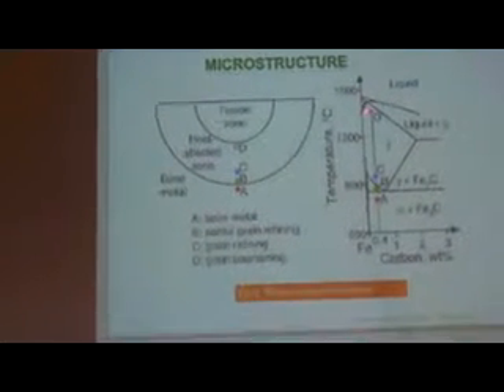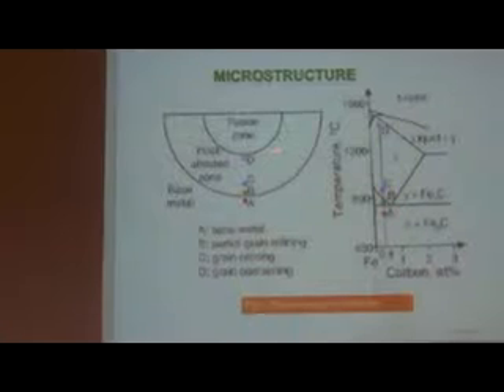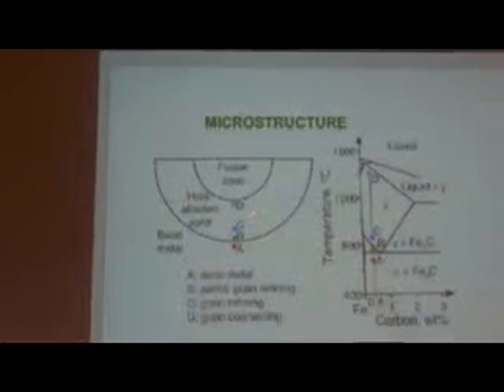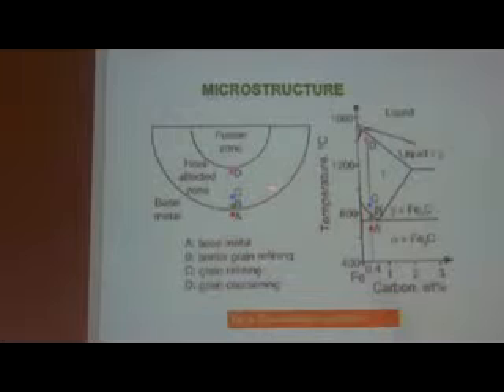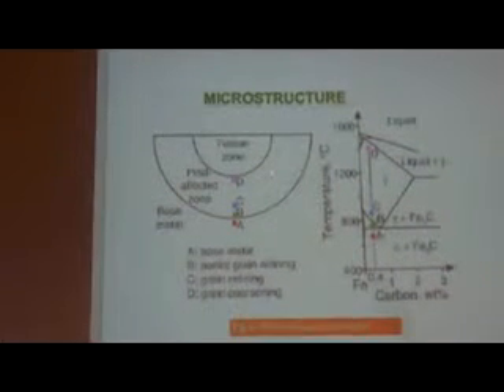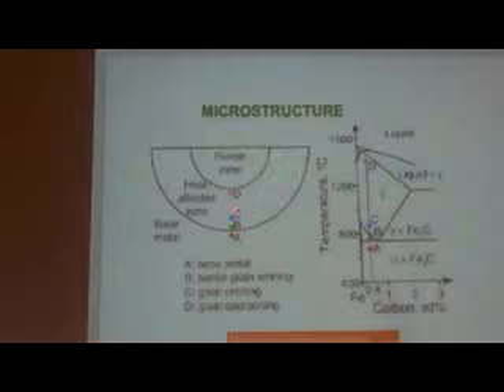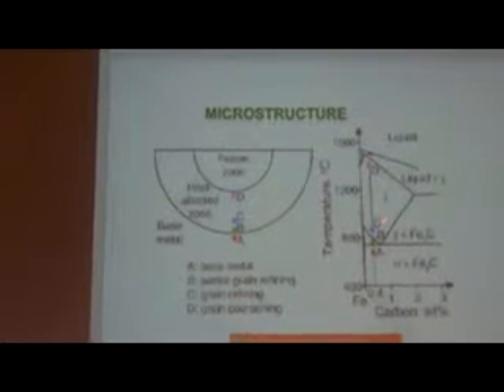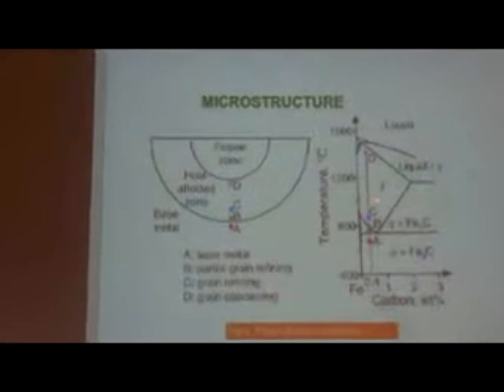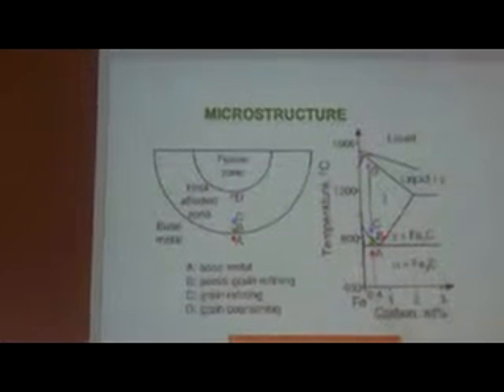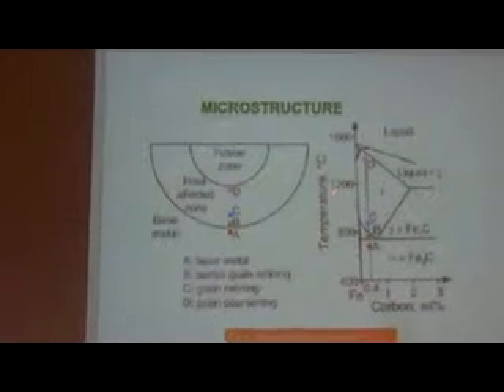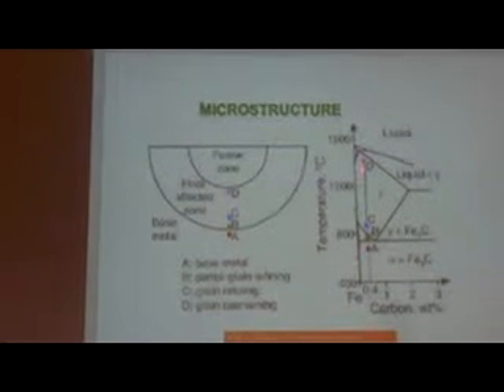So in your weld metal, next to the fusion zone, the point located at D offers a higher temperature next to your fusion line, that is, the peak temperature is higher. That is the reason it offers a grain coarsening kind of structure. Whereas coming to the next point, here we have an intercritical temperature region, where your material will undergo different kinds of microstructural transformation. That is this region C, where the temperature is above 727, that is above A1, but below your high temperature line.